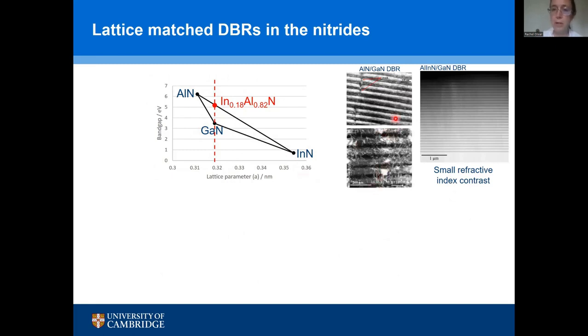This is what goes wrong when I make distributed Bragg reflectors out of aluminium nitride and gallium nitride. Because the aluminium nitride is in tension on the gallium nitride, it tends to crack. And that means we get lots of variation in layer thickness in the stack. And you also generate lots of defects.